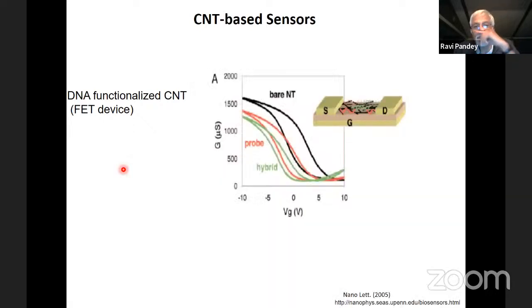So what you do is you have this cartoon. The DNA functionalizes the carbon nanotube, and this is our sample. We have source and drain, and this is our gate field, applying the gate. If I look at the conductivity versus the gate voltage, I can see the bare nanotube has certain characteristics in black. If I functionalize it with the DNA, which I call the probe, in orange, it again has distinct characteristics in terms of the conductivity, gate voltage curve.